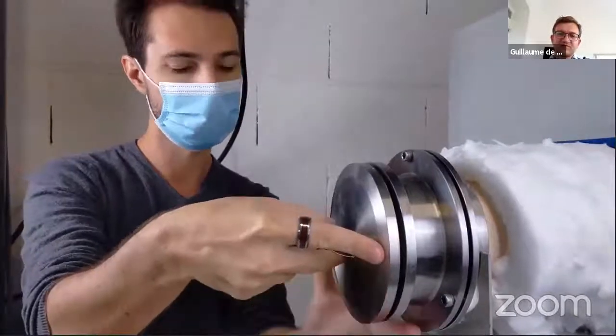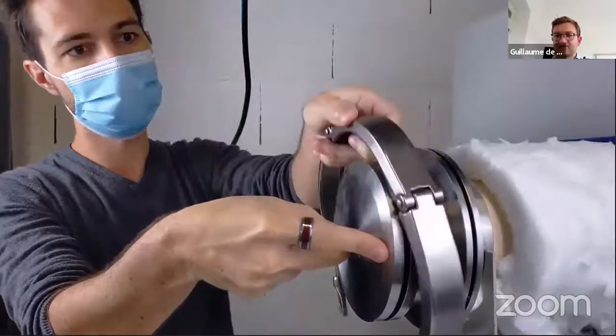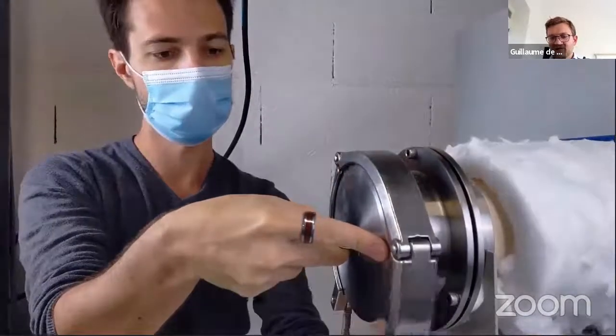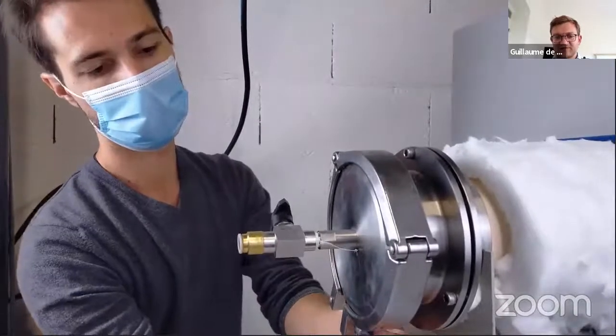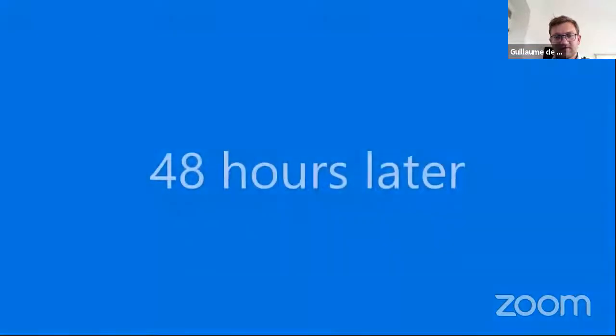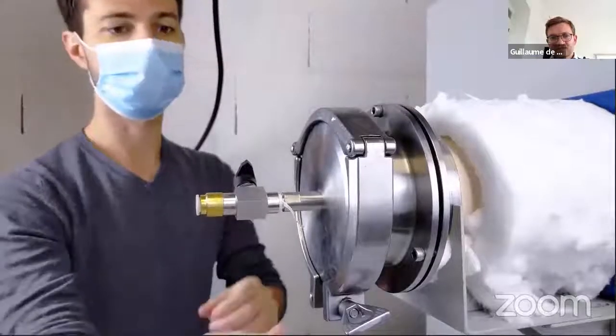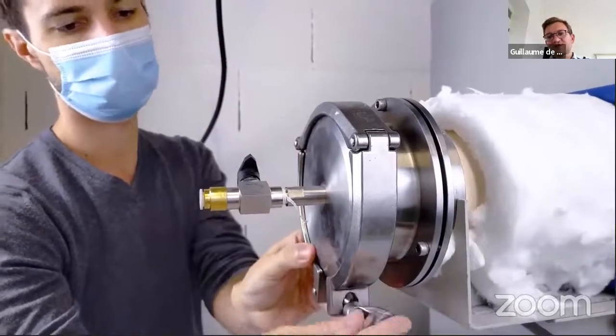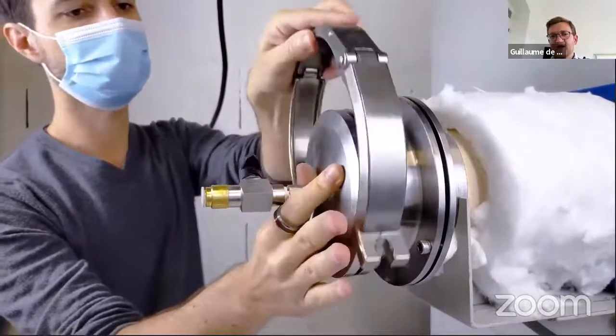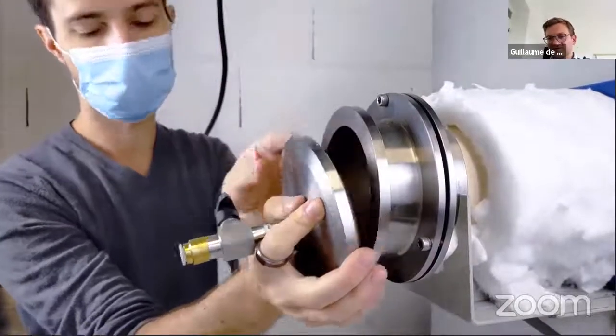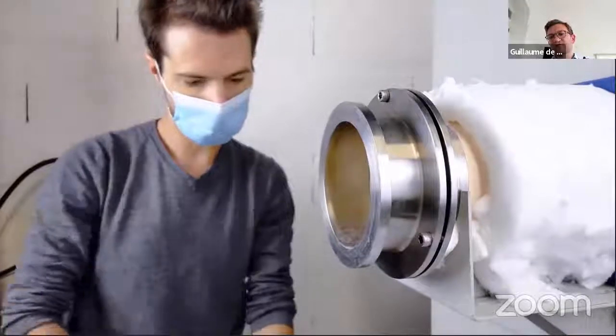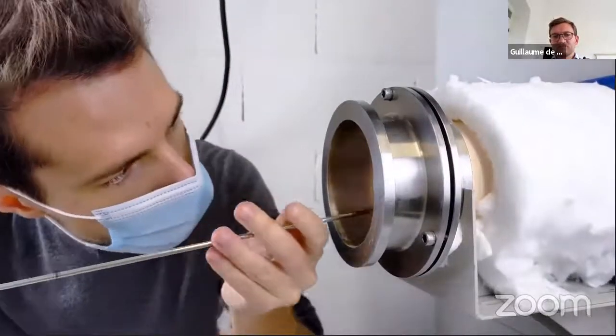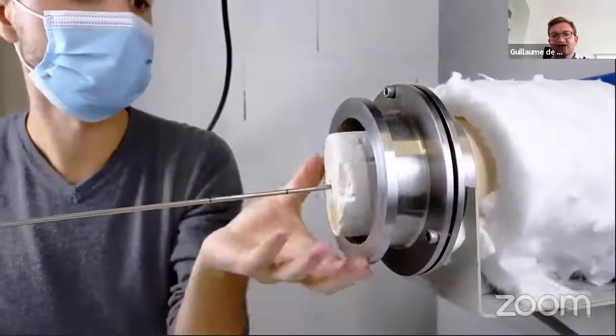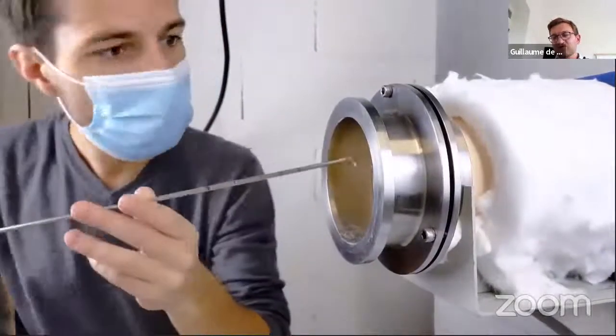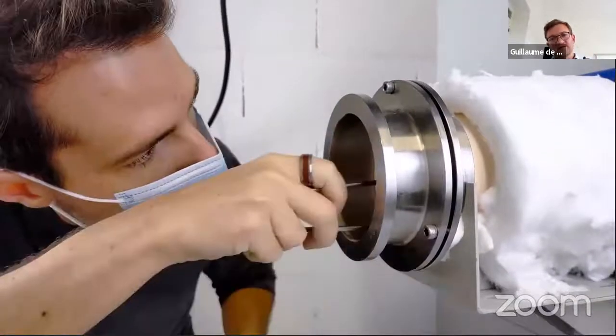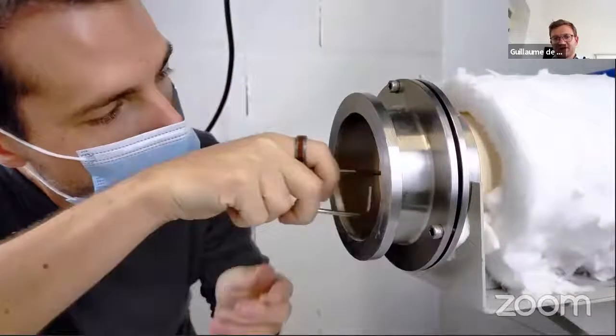Here we're showing the setup that we would use for metal sintering. So we would close the furnace completely and have a flow of gas go through the material. You can see here it's quite simple. You just have to plug the gas flow on it. And the sintering takes between 24 and 48 hours, depending on the thickness of the part. Usually it's more in the range of 48 hours because of the thermal debinding more than the sintering itself. I didn't precise it, but you do have here what we call a heat shield. It's a porous ceramic that will keep the heat inside the furnace, and then you can get the part out.